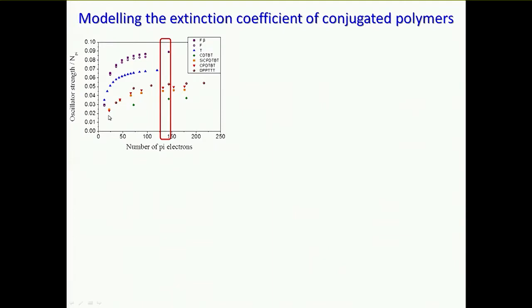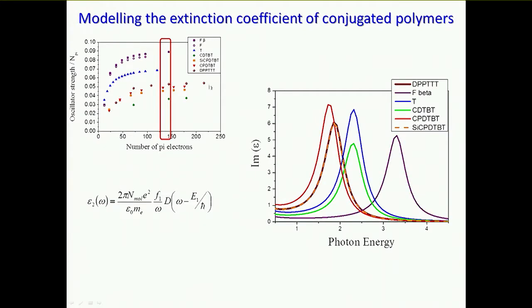But then we thought, oh, hang on a minute. These are wide bandgap materials, so oscillator strength is going to be high, but refractive index would then need to divide by the transition frequency. So let's have a look at the imaginary part of the dielectric constant instead, and that should then show us better the advantage of DPP TTT. So we did that, and here is DPP TTT, and still it's more or less nowhere. It's not by any means the strongest absorbing material.